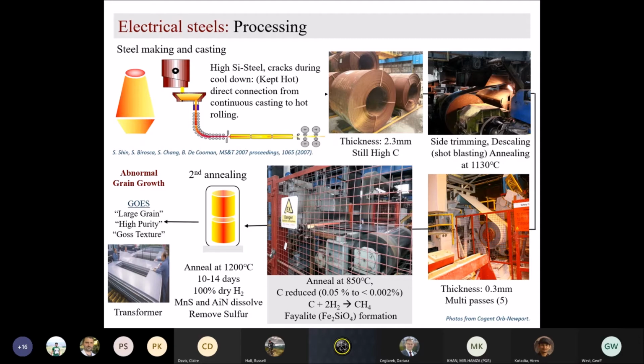And also, we need clean steel. So what we do, we decarbonize it, as we call it, primary annealing. At this primary annealing, you do primary annealing at 75% hydrogen, 25% nitrogen, and water vapor as well. So the chemical reaction, I put it there for you.